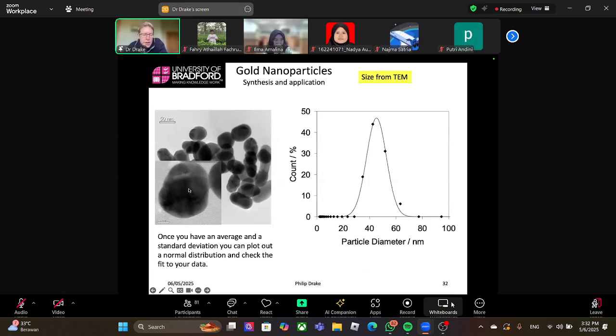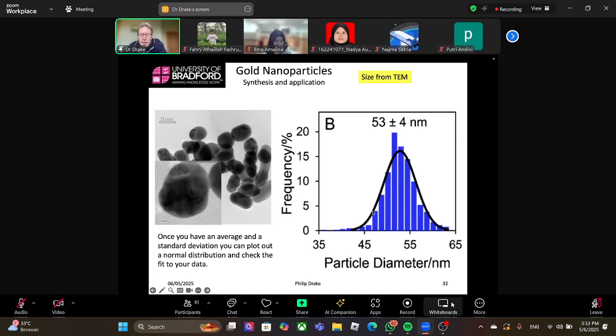We could do that with bigger particles too. So here we have 50 nanometer particles about. If we take lots of particles, we can measure the particle size using a ruler or using software. We can put out a normal distribution curve, and we can look at the frequency distribution with the points. So the histogram is our frequency distribution. We look at bin sizes and plot out how many particles within that range. And the black line is the normal distribution fitted to an average and a standard deviation. Once you know an average and a standard deviation, you can plot the normal distribution and make sure that fits to your data. It should be a bell-shaped curve.